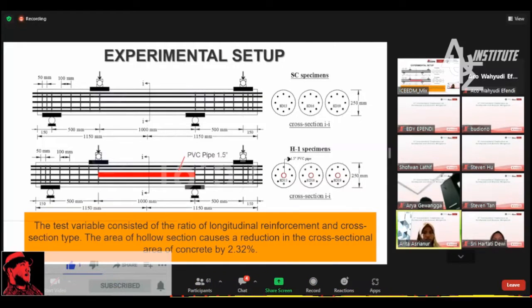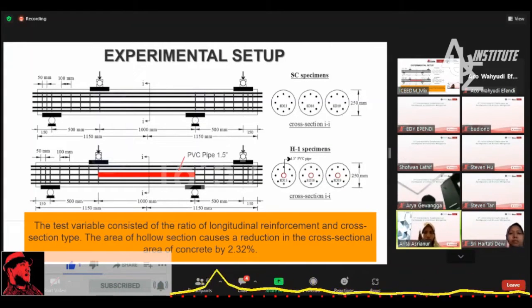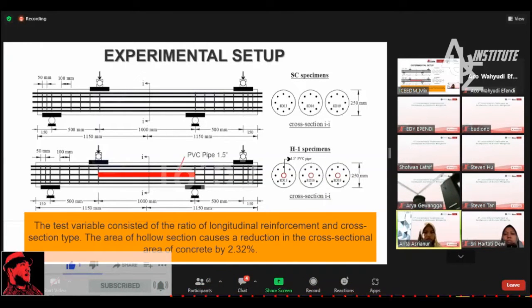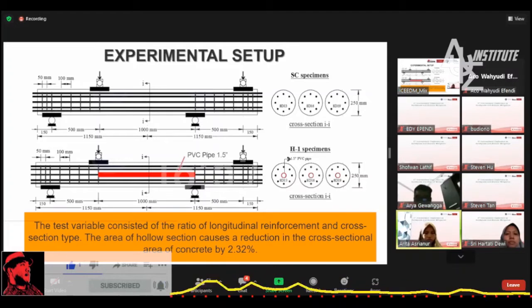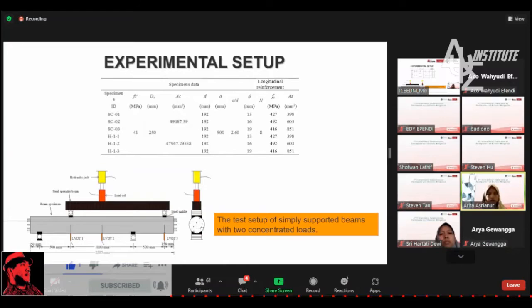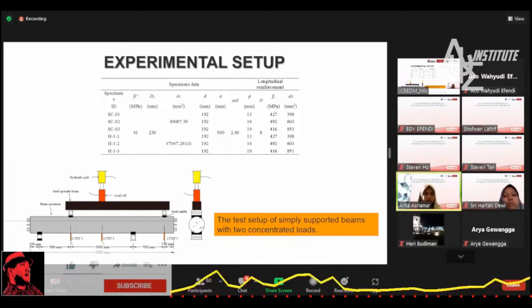This page shows the specimens tested in this study. The test variables consisted of the longitudinal reinforcement ratio and the cross-section type, that is with and without hollow. We can see the area of hollow section causes a reduction in the cross-sectional area of concrete by 2.32%, which means that the hollow in this specimen is less than 4%, which is below the provisions. As shown in the figure, all of the specimens were not reinforced with stirrups. And this table contains the material data for each specimen.